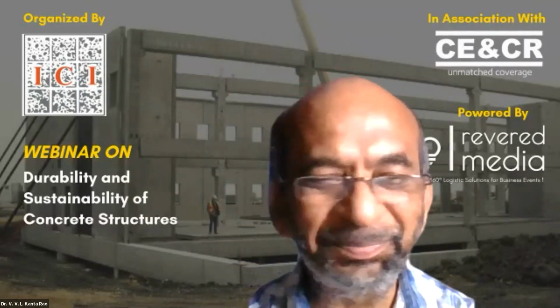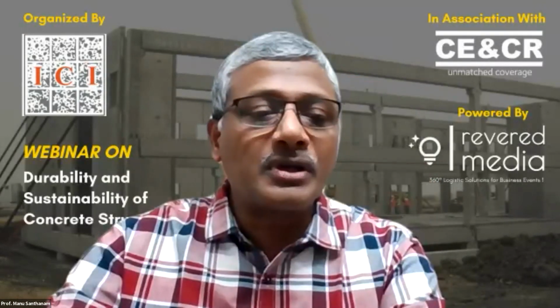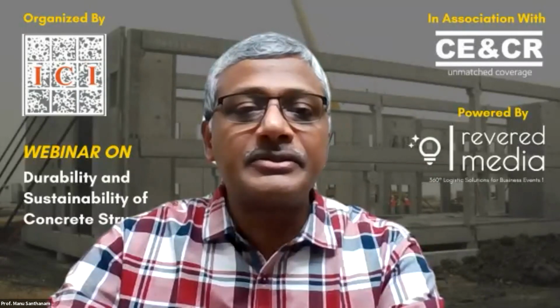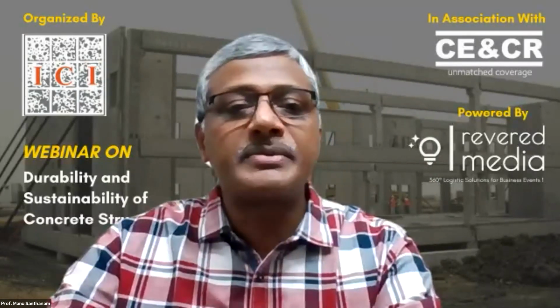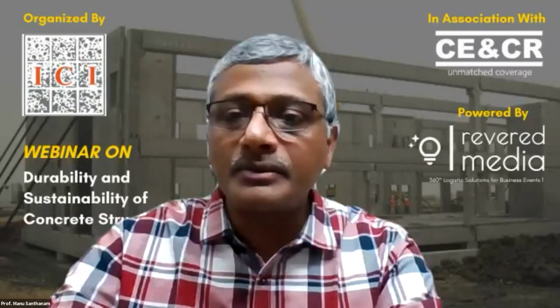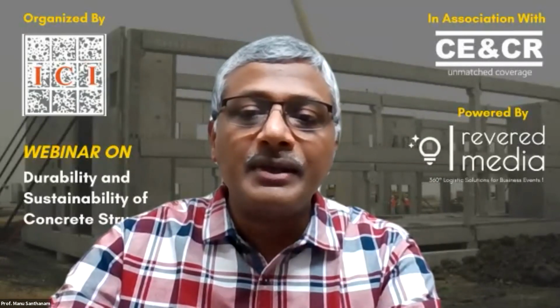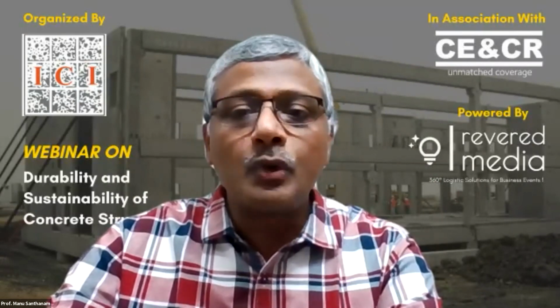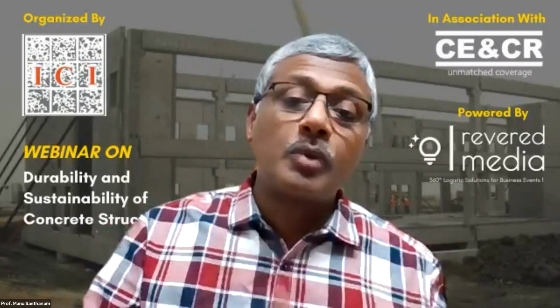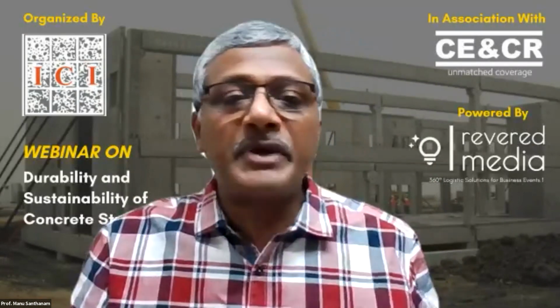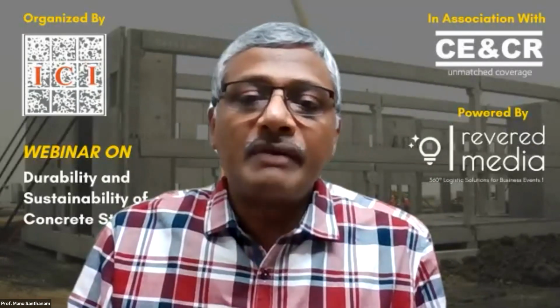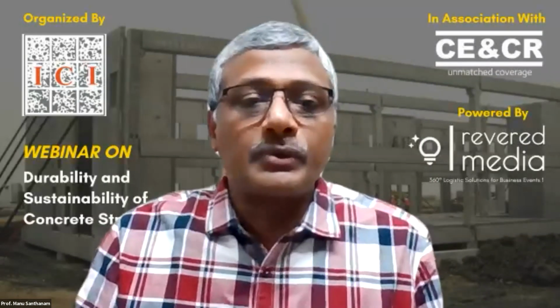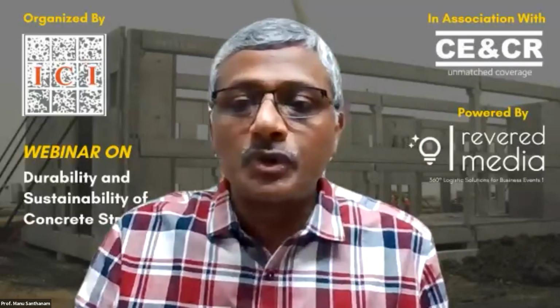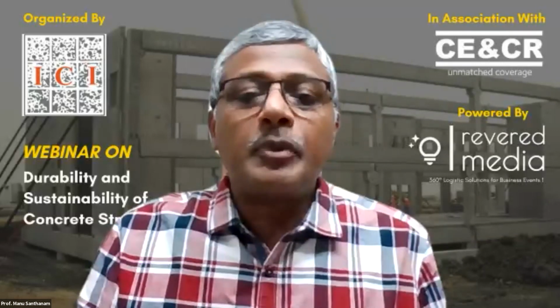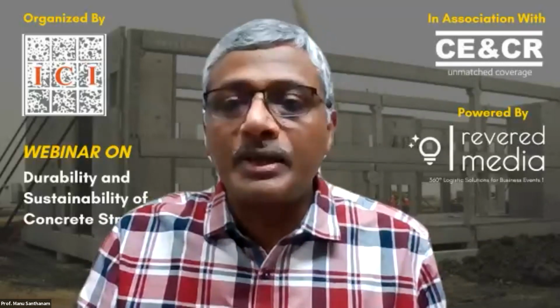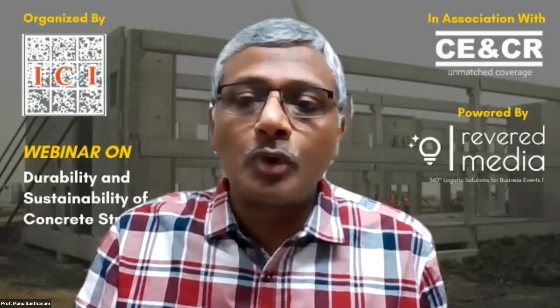Yeah. No, see, the porosity of the concrete is what needs to be reduced. And for that, the choices, of course, are to use a low water to cement ratio in the system, provide adequate curing, just like we do for ordinary Portland cement concrete. In general, LC3 concrete will have a lower porosity, or rather, not a lower porosity, but a lower pore size as compared to plain cement concrete. When you have a lower pore size, the pore connectivity reduces, and that leads to a better transport characteristic that reduces the problems in durability, like chloride ingress and things like that. Right. It makes concrete more impermeable. Yeah.